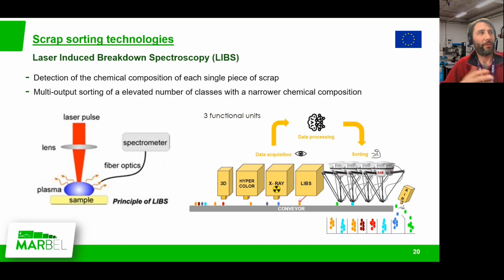In order to improve this selection, there are some technologies that are being developed, and some of them are already implemented in industrial sites, still under development, so they are not fully deployed and not commercially available, but there are several solutions working on this. One of them is selection and classification techniques based on LIBS, laser-induced breakdown spectroscopy. With this technique, you have a measurement of the chemical composition of each single piece of scrap.